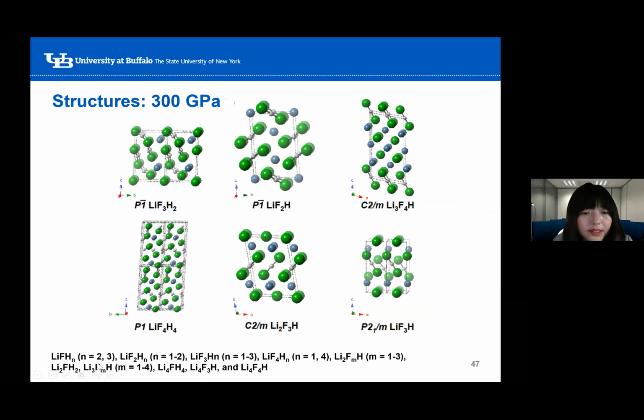A full list is listed here. So we identified six structures out of them within 50 meV per atom above the hull. There is no thermodynamically stable structure, because all of them would finally decompose into lithium fluoride at 0 Kelvin though. So we listed all the metastable structures from the lowest enthalpy one to the highest enthalpy one.